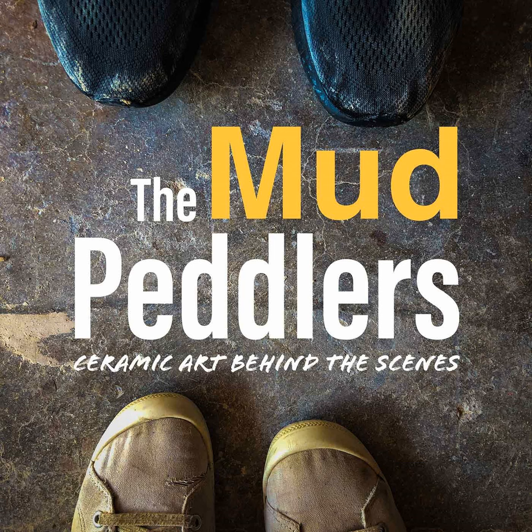It's interesting to see glazes I develop that are on the edge of too much or too little alumina. Matte finish is really just alumina developing and making a sheet. Sometimes I tell people: just fire in a bigger kiln, give the alumina more time to develop at a lower temperature than your peak firing temperature — it'll probably come out more matte. Some of my glazes with a little more alumina than silica will sometimes turn matte in my bigger kiln when they came out relatively glossy in my small tester kiln.